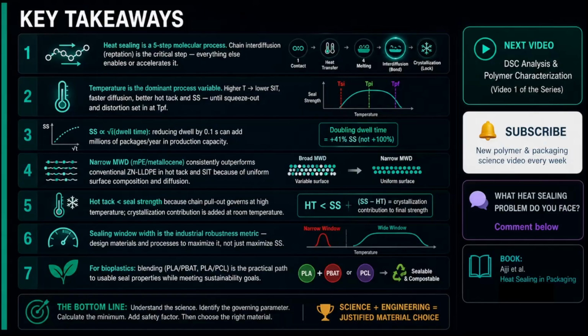7. For bioplastics, blending PLA with PBAT, PLA with PCL is currently the most practical path. No single bioplastic sealant offers comparable sealing performance to optimized conventional polyethylene. The blends are the compromise that makes sustainable packaging commercially available.